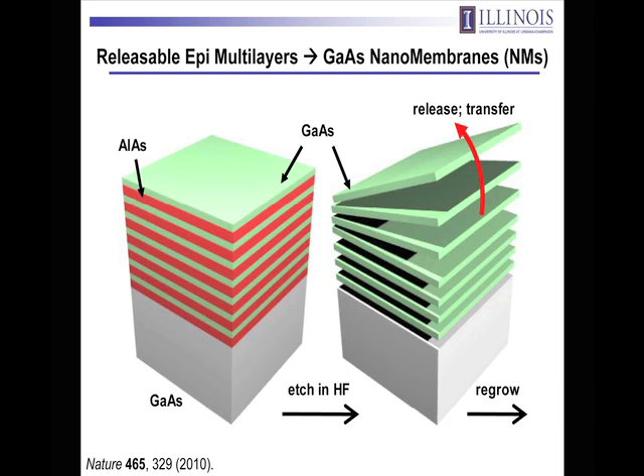In this case, we start with a gallium arsenide wafer, and then we do MOCVD epitaxial growth of alternating layers of high aluminum content gallium aluminum arsenide and gallium arsenide itself. You can grow purely epitaxially very thick multi-layer structures like that, which are interesting because if you etch down through that stack to expose the sidewalls and you dunk it in HF, HF will etch away the aluminum arsenide at a rate that's about a factor of a million times faster than it will etch gallium arsenide. The consequence is you lift off, from the underlying growth substrate, multi-layer stacks of gallium arsenide nanomembranes. Again, semiconductor-grade monocrystalline materials that are interesting as building blocks because of the mechanics I talked about in the previous slide. And oh, by the way, you don't consume the wafer, so you can come back and do this growth again.